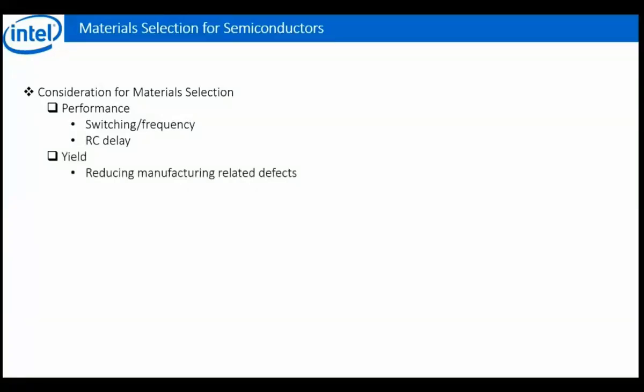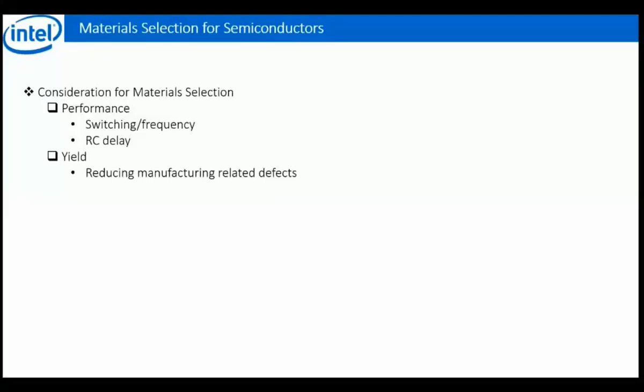The second major thing that we need to focus on is yield. And this relates to how we actually create these semiconductor chips. We create these in clean room factories, right? So clean rooms are basically spaces where the particle count in the atmosphere is extremely low. So it's in the ppb, parts per billion. And even further down the line, right, we want to decrease it as much as we can. And it's not enough to do that. We also need materials that go into the chip that do not easily interact with the materials outside. It could be the environment outside, or it could also be the tools that are used to make these CPUs. So the thin film deposition, the electron beam lithography, or CMPs, or chemical mechanical polishing, the dry etchers and the wet etchers and things like that. All those things, the materials have to be robust against contamination. So when it comes to material selection, that also plays a huge role.